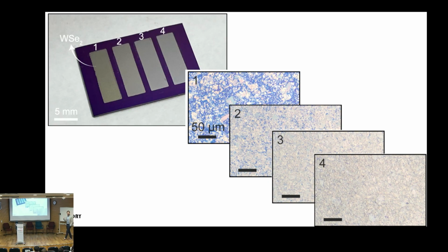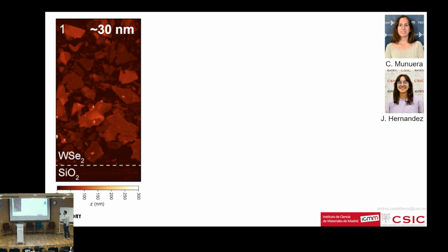So this is very important because if you want to make a film that conducts over large distances, you really need to do several transfers in order to get good percolation. But you can also, of course, do these things sequentially with different materials. So you can transfer a film of a semiconductor material, a film of an insulator material, and then make your stack on demand. So we have done, in collaboration with Carmen in the group, some AFM studies to see that indeed this is kind of adding up, right?